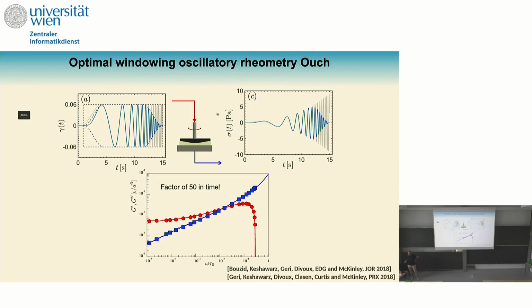So why don't we use this kind of signal in order to get the rheological response? The answer is yes. Instead of using just a sinusoidal function, what you can apply is a deformation that is modulated in frequency, but also in amplitude. You apply this type of deformation, you get the response, and then in just one simulation or one experiment, you can get the full viscoelastic spectrum.